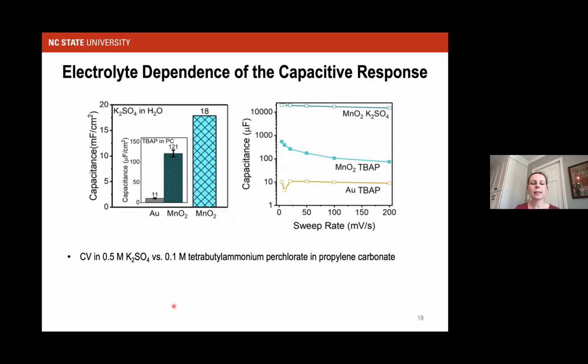We looked at the electrolyte dependence of this response from a couple of different standpoints. The first is to perform, in addition to what we did just before, the aqueous electrolyte experiments, we also did them in a bulky cation like tetrabutyl ammonium perchlorate in propylene carbonate. So no protons, no small intercalating cations present. And we find that the capacitance in that kind of a situation is orders of magnitude smaller than when we're in an aqueous electrolyte with a smaller cation like potassium.